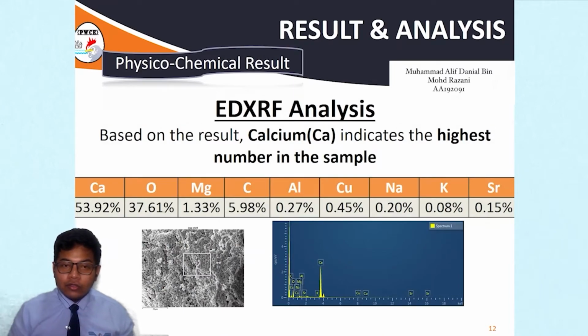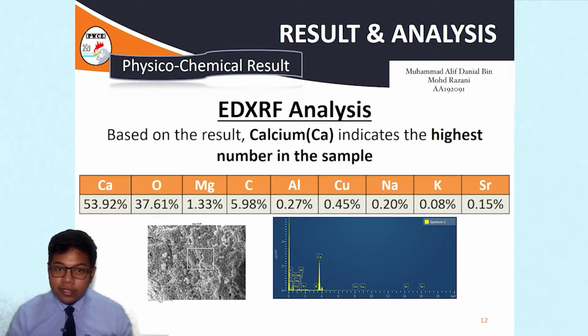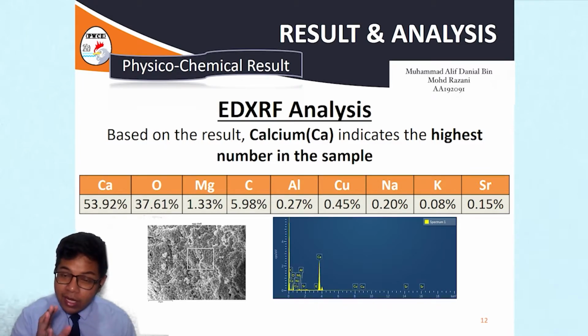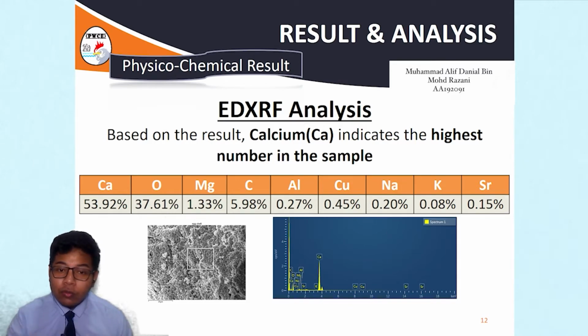Next, we also use the EDXRF analysis, which stands for Energy Dispersive X-ray Fluorescence. This test is one of two general types of X-ray fluorescence technique used for elemental analysis applications. If you look at the result, calcium indicates the highest number in the sample, with 53.92%. This further strengthened the hypothesis that eggshells are capable of removing phosphate from wastewater, as calcium is known as a good removal agent of phosphate.